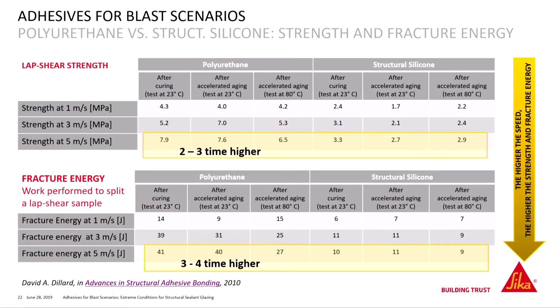Okay, then this was the comparison of the lap shear strengths. And when you look at the fracture energy, the work you have to apply to fracture the lap shear sample, it's even better. We have a 3 to 4 times higher value for the polyurethane.